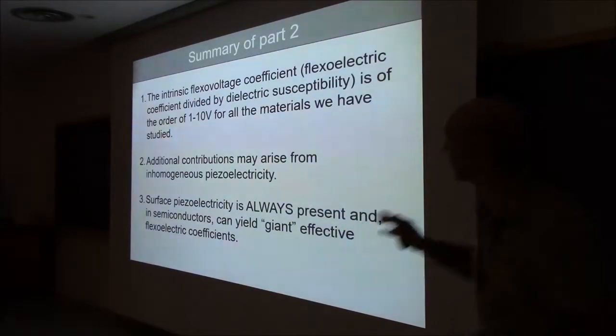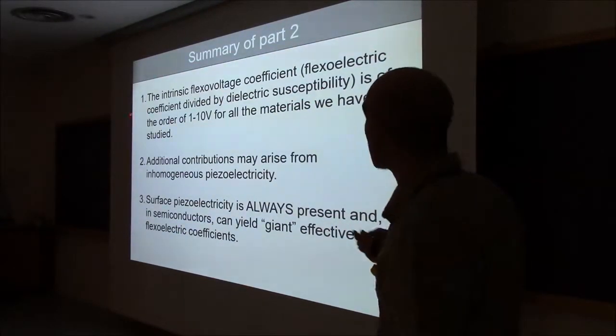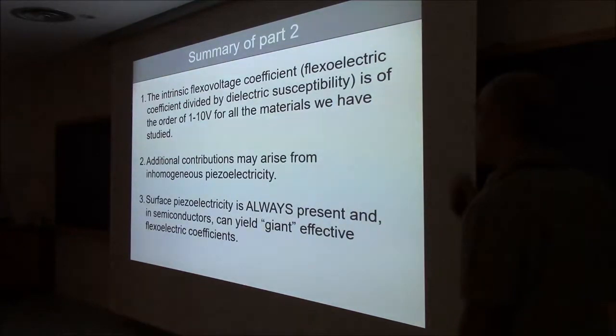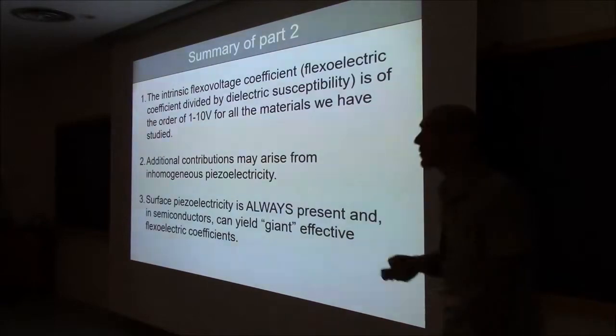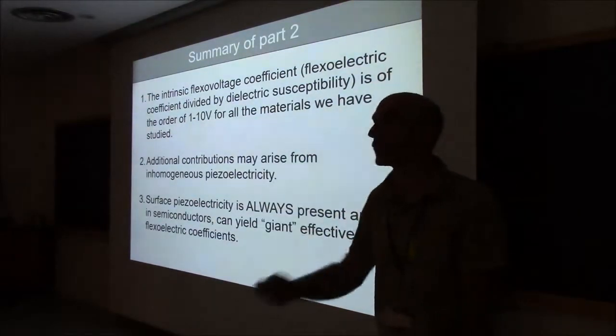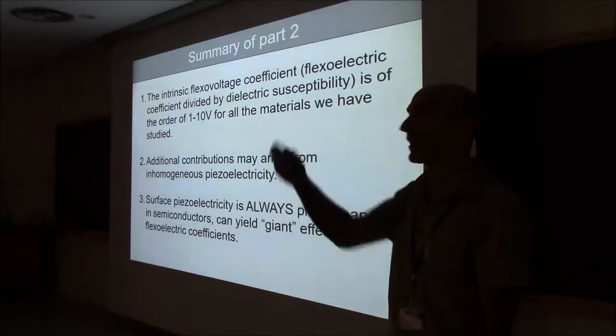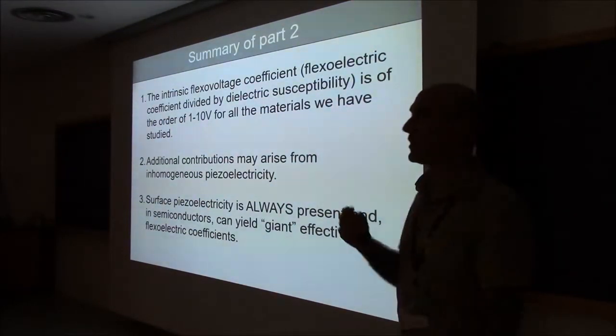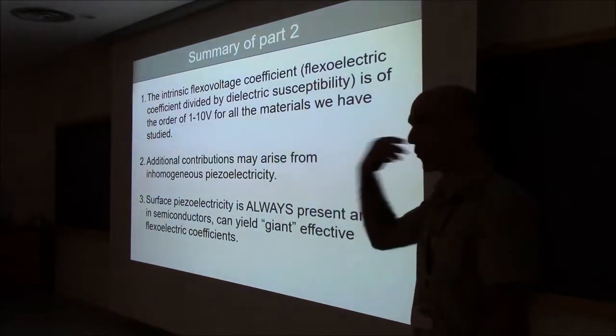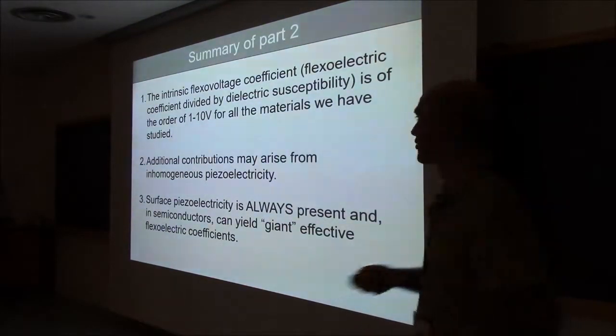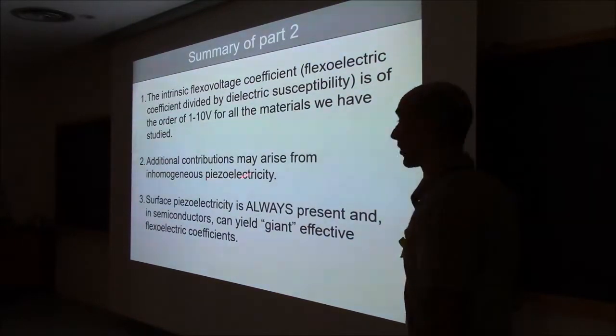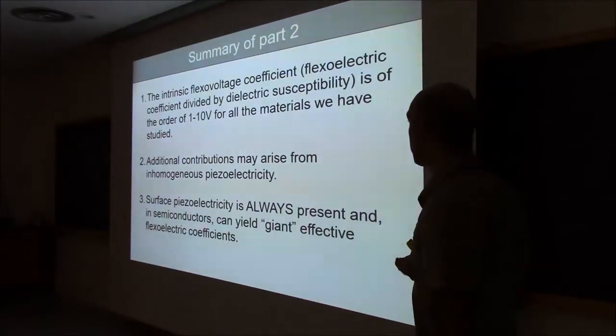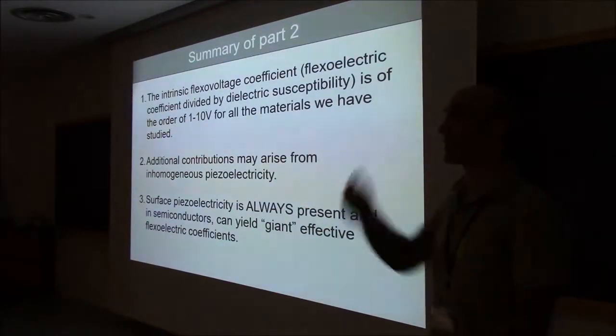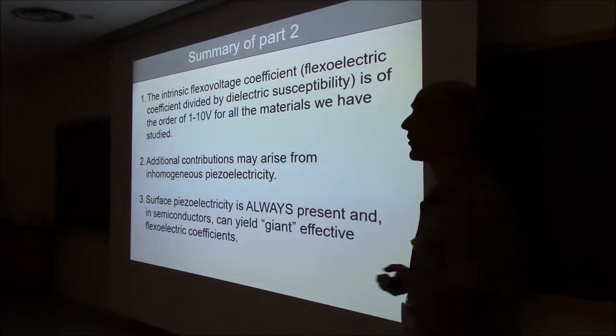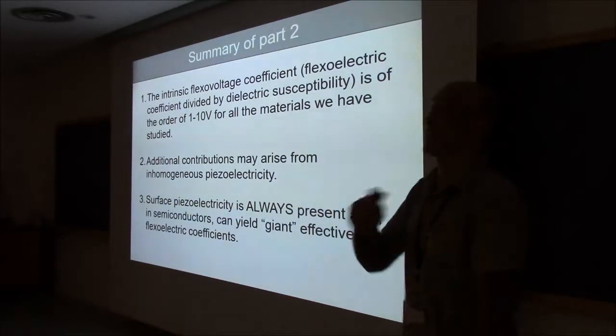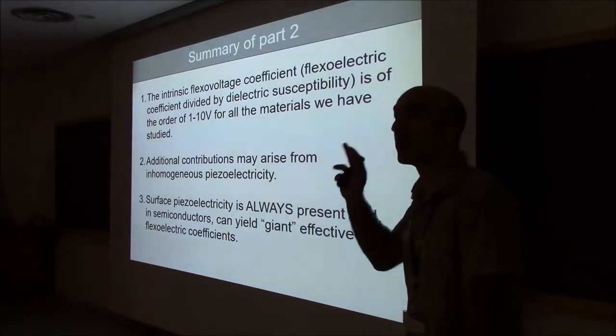Okay, so that brings me to the end of part 2. Take-home lessons. The intrinsic flexocoupling coefficient is always of the order of about 10 volts. So the intrinsic flexoelectric coefficient of your material will normally be 10 volts times its dielectric constant. That's lesson 1. Lesson 2 is if your material has any form of piezoelectricity, so polar nano regions, or if you are in a piezoelectric state, then you can have very strong additional contributions coming from this parasitic piezoelectricity. And then there's also surface piezoelectricity. This is always there, always. And in semiconductors, in fact, that is the very dominant effect. In fact, it's the only effect that you can measure.